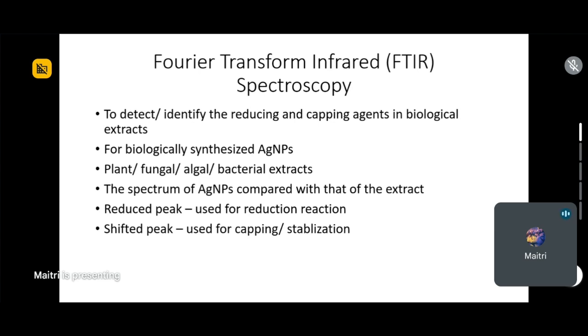Lastly, FTIR spectroscopy is to detect the reducing and capping agent for biologically synthesized AGNPs, obviously. And you need to run the actual extract which you used to form the AGNPs. And you compare the AGNPs spectrum, you compare the extract spectrum, then a reduction in a peak of the extract spectrum means that that compound in the extract has been used for the reduction reaction, whereas a shift in the peak in the AGNP spectrum compared to the extract spectrum means that it has been used for capping or stabilization.